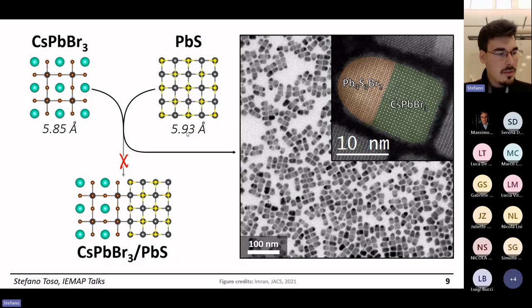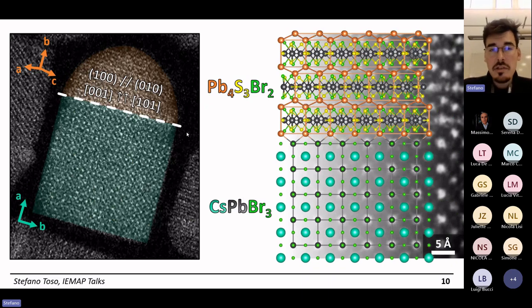We did get some heterostructures. The material was not the one expected. But when we went into the characterization and studied the interface, we sort of figured out why it was forming. I mean, if you have a look at the structure on the right, you do see that the two materials match really well. They also contain the same atoms. Basically, you have lead, you have bromine. Okay, there is sulfur here, there is cesium here, but there are clear similarities that do allow these two materials to grow epitaxially. The problem is that we didn't know. And if we knew, maybe we would have designed the experiment in a different way. So this triggered the development that now I want to show you.